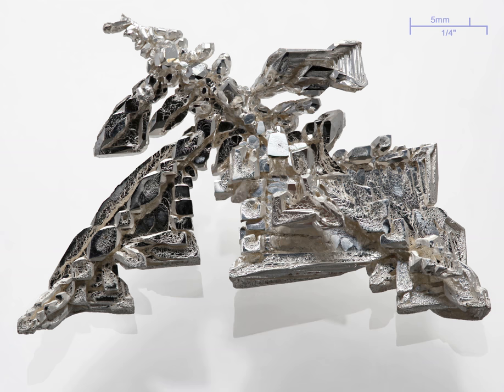Base metals like zinc, cadmium, silicon, and germanium do not totally prevent corrosion and tend to affect the luster and color of the alloy. Electrolytically refined pure silver plating is effective at increasing resistance to tarnishing. The usual solutions for restoring the luster of tarnished silver are dipping baths that reduce the silver sulfide surface to metallic silver, and cleaning off the layer of tarnish with a paste. The latter approach also has the welcome side effect of polishing the silver concurrently.